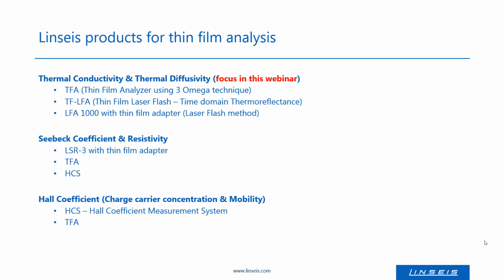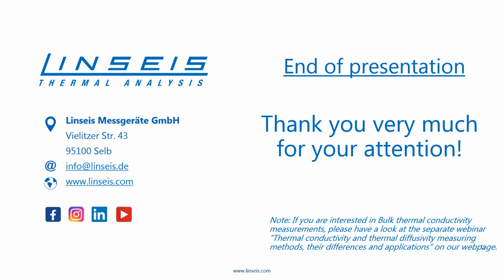The Seebeck coefficient and resistivity can be obtained by the TFA, the LSR using an adapter, or one can also use the Hall characterization system for determining the resistivity. The Hall coefficient can either be measured by the TFA or the just mentioned Hall characterization system.